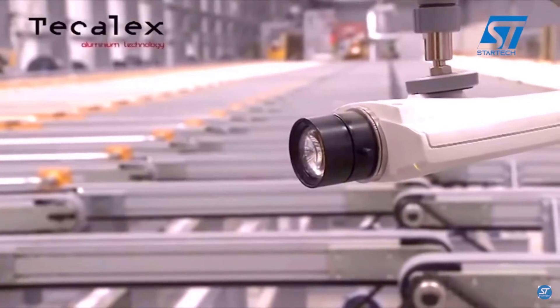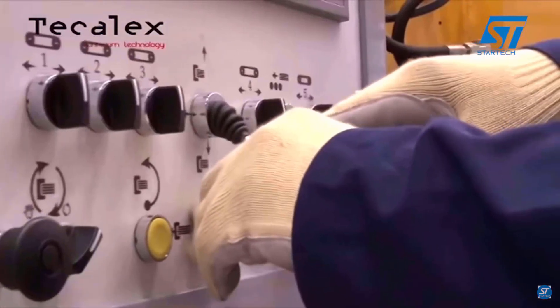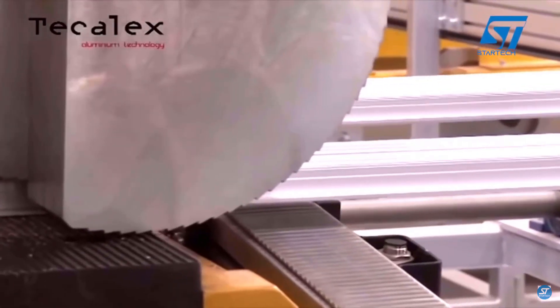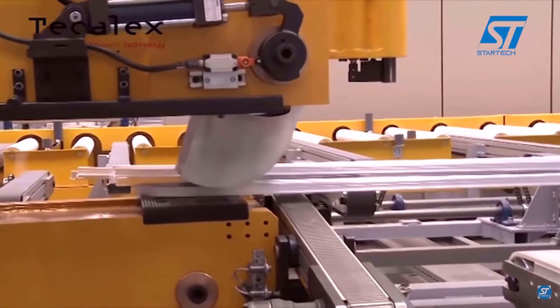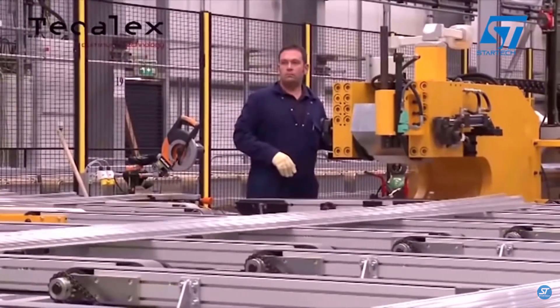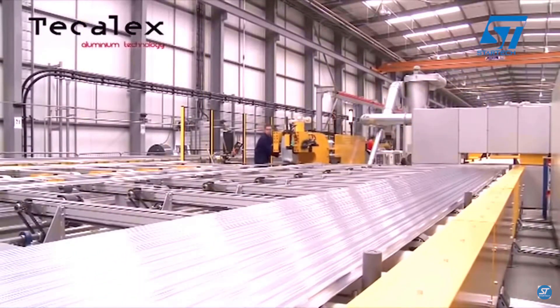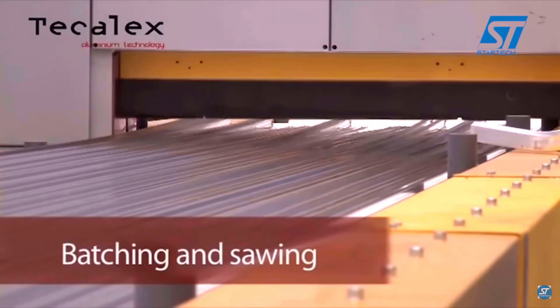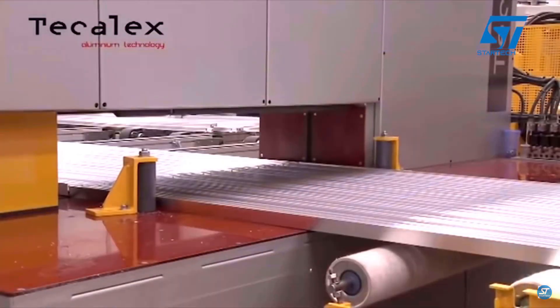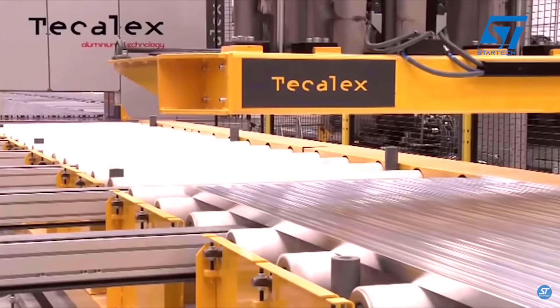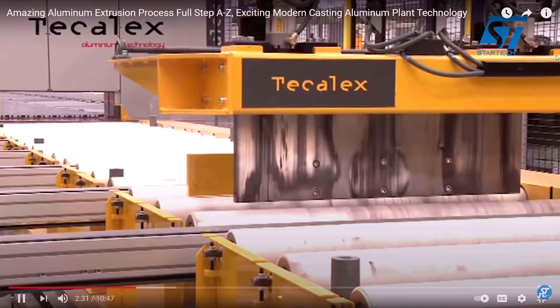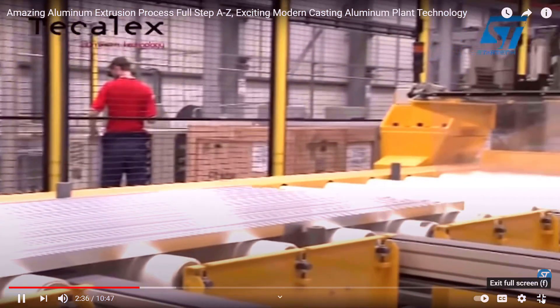They're grabbed by a machine that trims the extruded parts. They go down a conveyor where they get stretched, and this is why aluminum profiles are so straight. Machines will clamp on either end of the profiles and then stretch the material about three percent, and it's that stretching that straightens the aluminum material. It's like pulling a string. After they're stretched, then the ends are trimmed. You can see the ends - they're not straight, that's where the machine grabs it to clamp it.